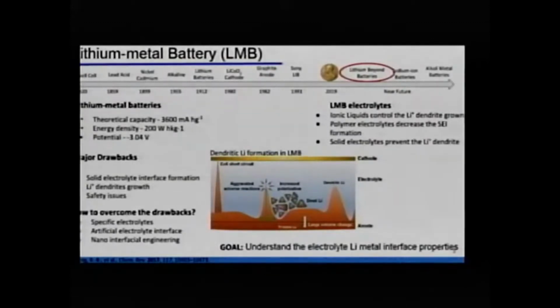Since we have the deposition of lithium ions on the metal surface, if this deposition is not homogeneous, we have the formation of dendrites. It's similar to having a bunch of lithium ions piled above each other. So there is the formation of something like a tree of dead lithium, or a branch that grows into the cathode. Once these dendrites reach the cathode, we have a short circuit and the battery explodes. So this is not a safe battery, but there are some ways that we can avoid the formation of these dendrites and the solid electrolyte interface.